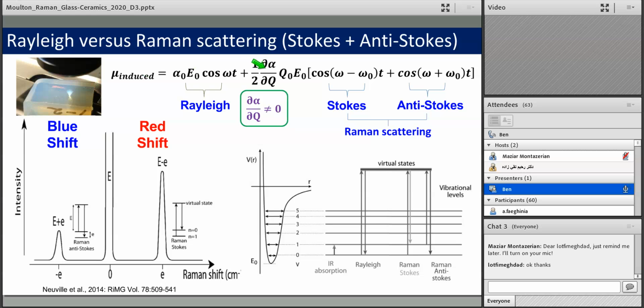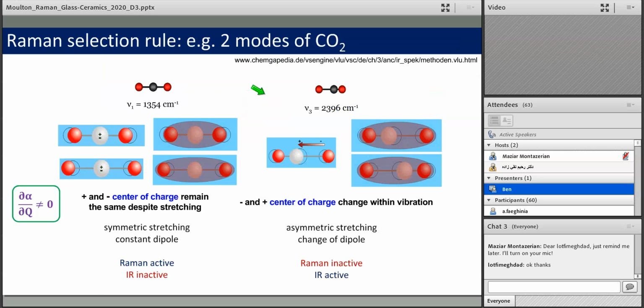So if there's a change in the ability to polarize the material, and a change in the displacement, which is just having a vibration, if this factor here is non-zero, we get the Raman effect, and we can have either Stokes or anti-Stokes. So the basic selection rule for Raman is that this quantity, delta alpha over delta Q, cannot be zero. And these shifts, as I remind you, are related to the frequency of the vibrations we just looked at. To put that in less mathematical and more figurative terms that are probably easier to make sense of, at least they were for me, here's a simple molecule of CO2.